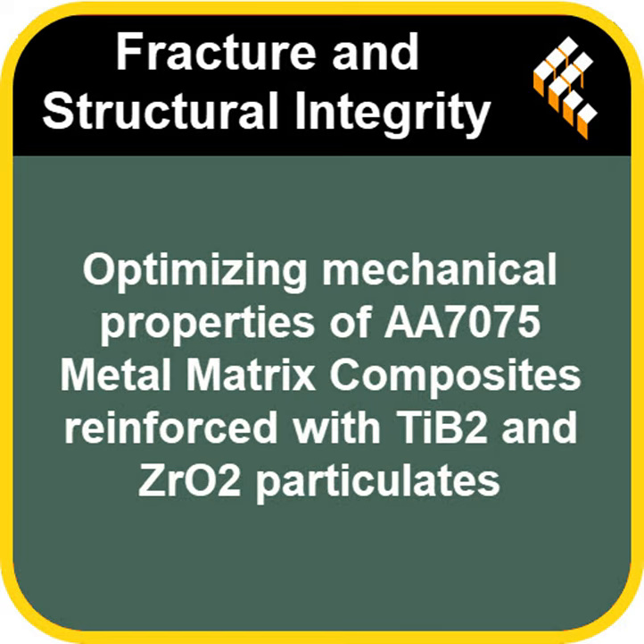Fascinating. So many interacting factors at that tiny scale. Okay, let's try and wrap our heads around this. What's the big picture takeaway here? If someone asks us what this research found, what's the core message? I think the central conclusion, the real insight, is that this specific combination, the AA7075 hybrid composite reinforced with 5 weight percent TiB2 and 4 weight percent ZrO2, really hit the sweet spot. It demonstrated the most favorable balance of properties: significantly enhanced mechanical strength, much higher hardness, and superior wear resistance compared to the base alloy and the other compositions.